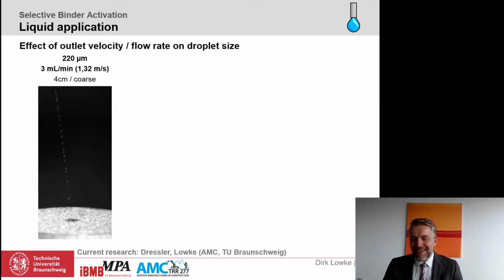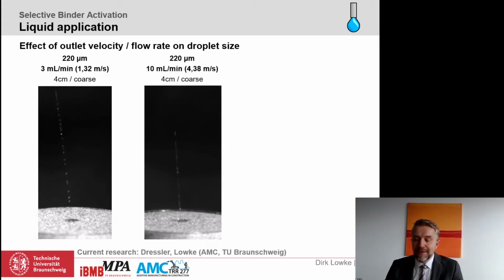Okay, let me start to show you some slow motion videos of the liquid application process. Here we use a 220 micrometer nozzle and a flow rate of 3 milliliters per minute. In this scenario, the water appears as small droplets on the surface of the particle bed. Now let's have a look at a second video. Here we increase the flow rate up to 10 milliliters per minute, and you can see that the breakup length increases and the water now forms a continuous water jet.